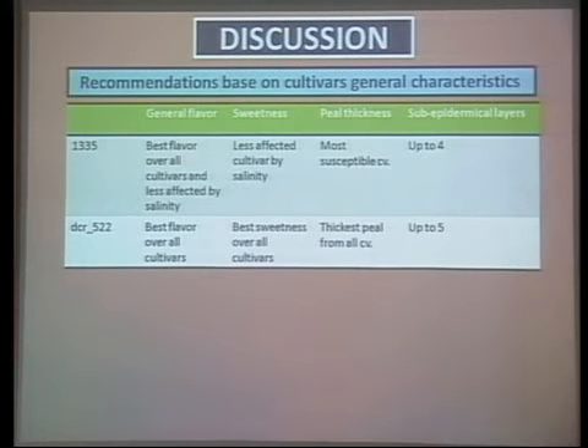Just to put it all together, we decided to start with the cultivars that the consumers like the most. They like 1335 and DCR 522 more. The problem is that these cultivars are the ones that are most susceptible regarding peel thickness, and DCR is the one that has the thicker peel from the consumer's point of view. This was reflected in the light microscopy because they have up to 4 or 5 subepidermal layers when grown under salt stress conditions. We suggest that these two cultivars be further studied to improve their salinity